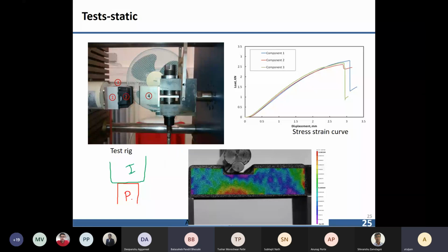Yes. When you apply a bending load, you are never going to get full indenter contact with your specimen in the initial steps. Initially, there's only going to be contact in some places between the indenter and the sample. After you apply a certain load, the contact is full. This is very standard. This will always happen when you do bending tests: the slope is going to be very low because contact between the indenter and the sample is not complete. After some load, when the contact is complete, this is the actual load displacement curve slope.